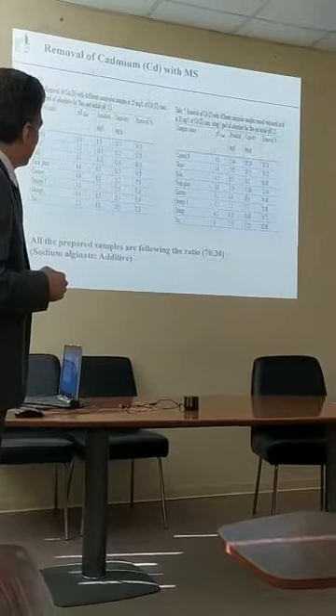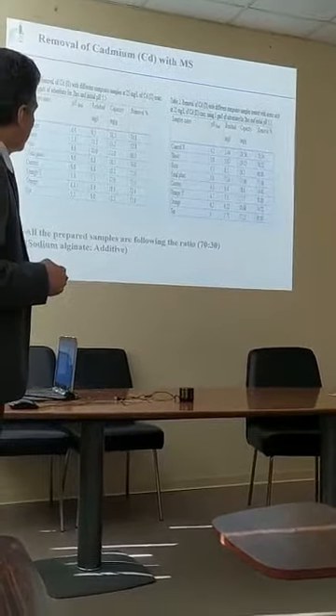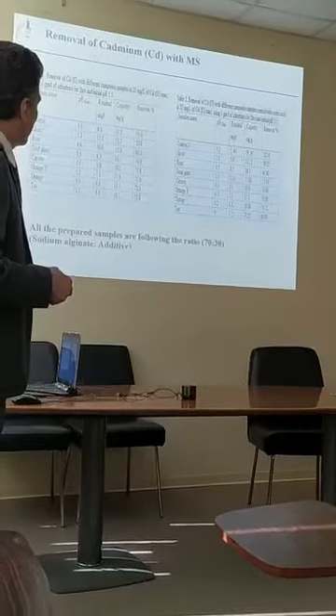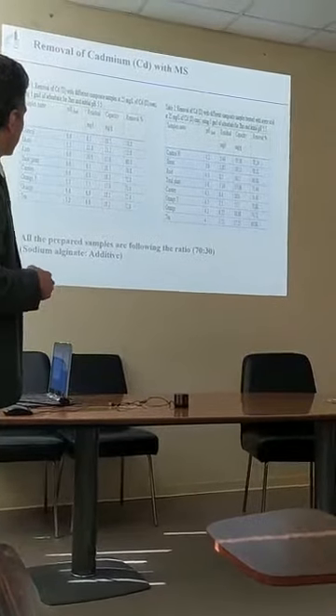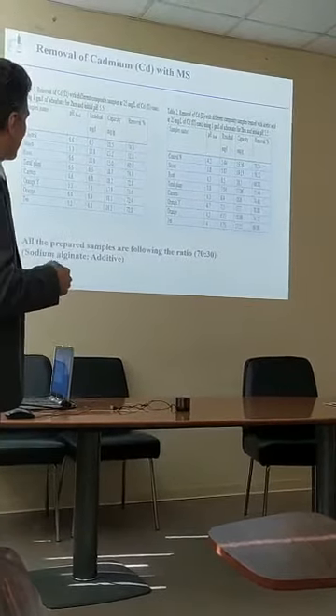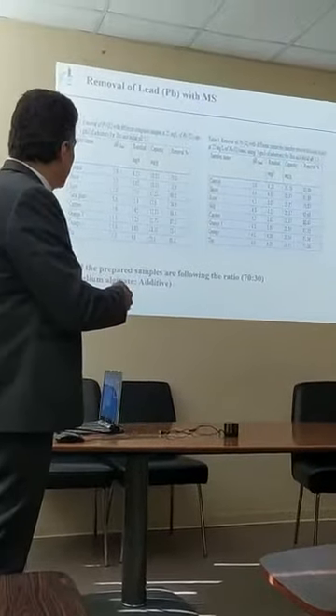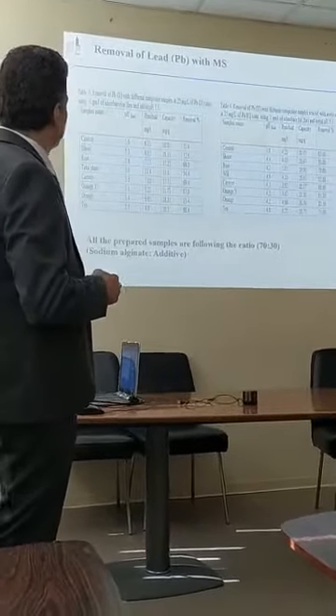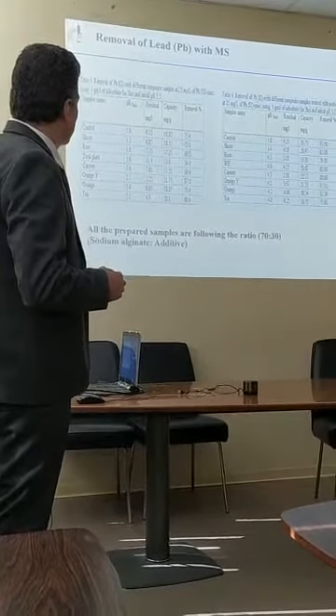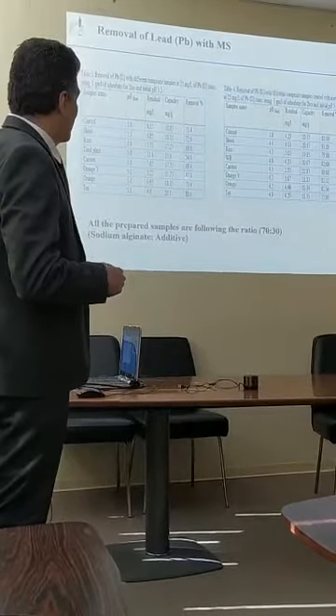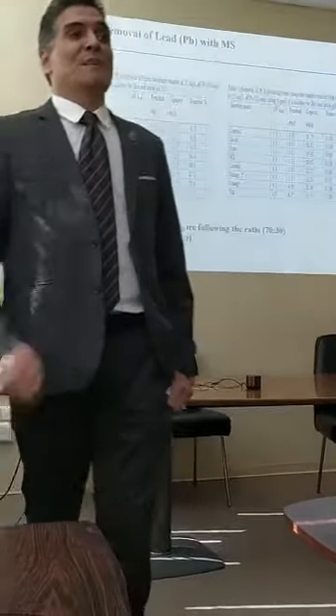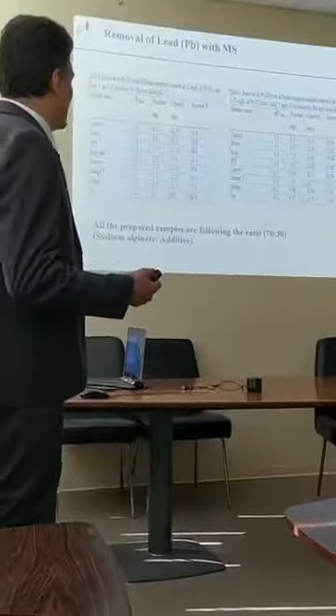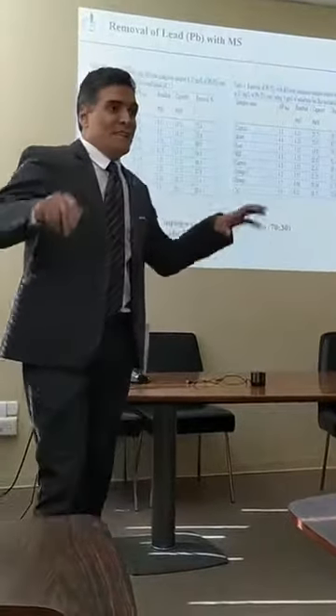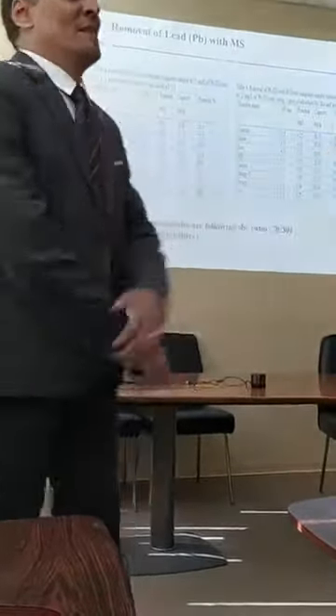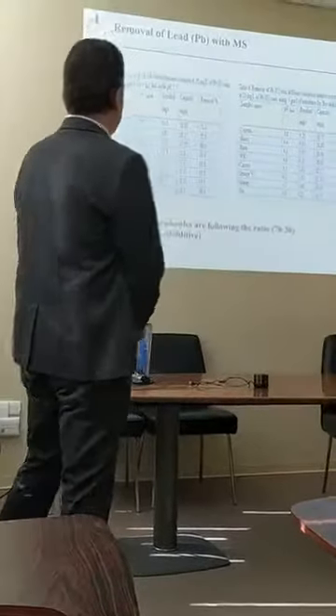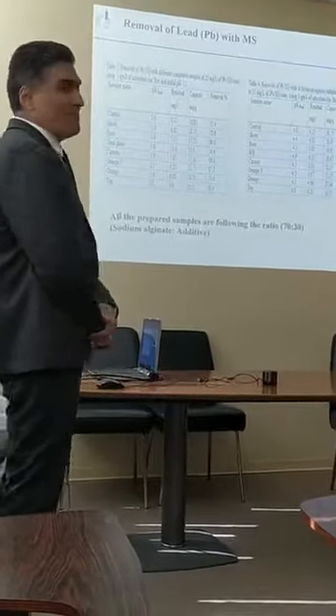We have also here the cadmium. Okay, the removal of cadmium, this is the rate of removal in 2 hours. Okay, this is for 2 concentrations of cadmium. One is high concentration, other is low concentration. And this is the results of lead. Okay, the removal in orange is 87% could be removed in 2 hours, which is a big amount to be removed. If we speak about 2 stages, we can eliminate lead from the wastewater with this kind of microsphere.